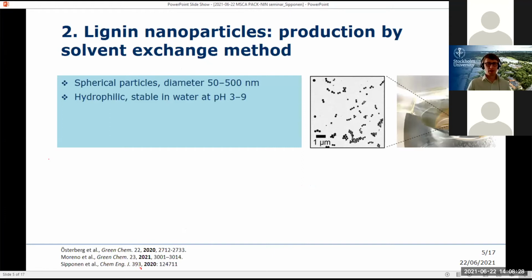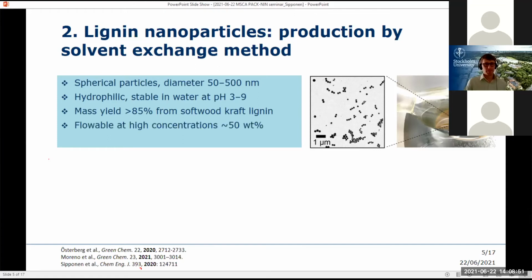They are hydrophilic from the surfaces, so they are charged and stable in water in a pretty broad pH range, excluding the extreme acidic and alkaline conditions. They can be produced in a relatively high yield, and this is a non-covalent synthesis, so we don't need any chemical functionalizations. Then these particle dispersions can be concentrated to relatively high concentrations. However, this is dependent on the particle size and other properties, which need to be controlled pretty carefully.